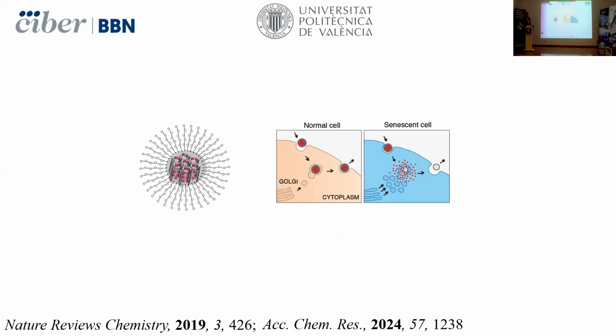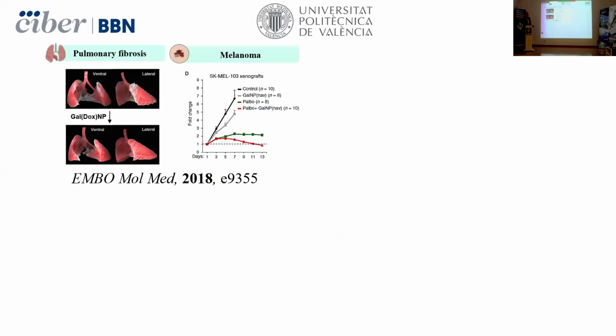So then we have a system that targets senescent cells. It's quite simple. In normal cells, the nanoparticles will arrive at the lysosomes. There is a low concentration of beta-galactosidase, and therefore no delivery of the cargo, but in senescent cells, in the lysosomes, there is a high concentration of beta-galactosidase that will uncap the pores and deliver the cargo. So we have applied that for many, many different systems.